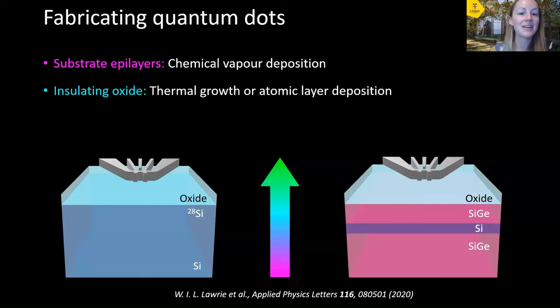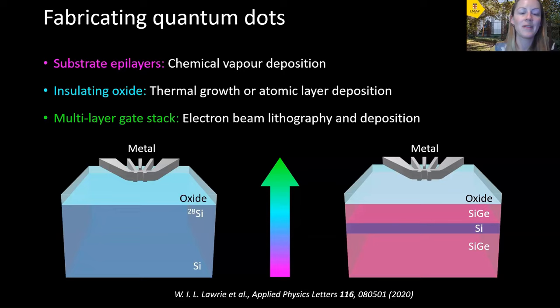We would then create the electrically insulating oxide layer, either by simply heating up the silicon in oxygen to grow a thermal oxide, or by something called atomic layer deposition, where you can deposit a dielectric material to insulate it. And then finally, we finish off by building a multi-layer gate stack by using multiple layers of patterning using electron beam lithography and metal deposition.